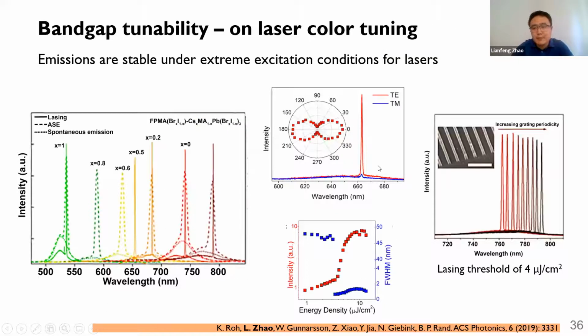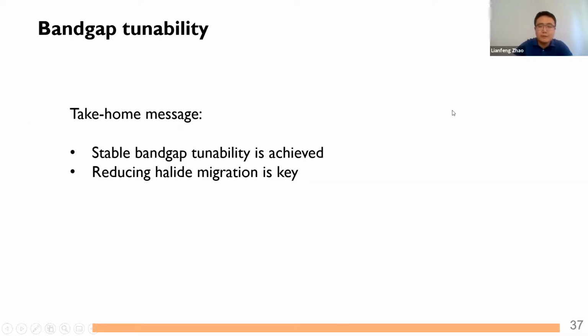In fact, our strategy can make the band gap tunability so stable that even under extreme excitation conditions, we were able to achieve a stable wavelength tunable laser based on mixed halide perovskite. So this really shows how stable our strategy is, as the excitation condition is far from thermal equilibrium for lasers. So for this part, the take home message is that the band gap stability and tunability is achieved using our strategy, and reducing the halide migration is the key.